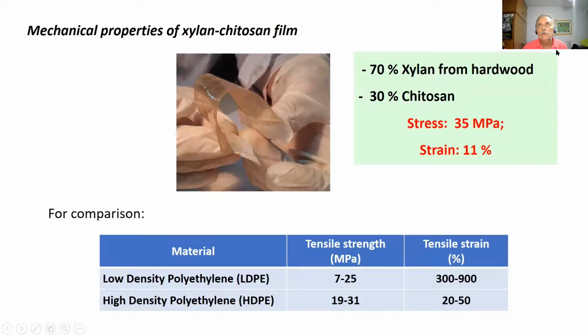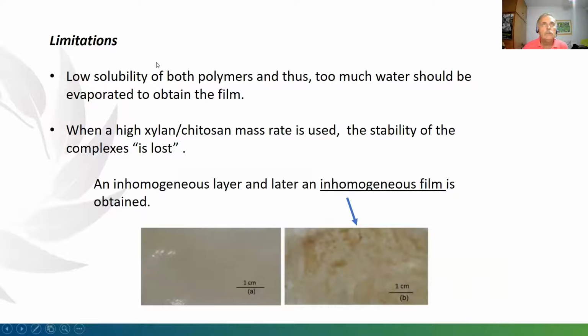And for instance, with 70% of xylan and 30% of chitosan, we have a stress of 35 megapascals and a deformation of 11%. This is not so far from commercial polymers, at least in strength and elongation, like high density polyethylene plastic. Which are the limitations of this xylan-chitosan system? First, low solubility of both polymers, and thus too much water should be evaporated to obtain the film. And when a high xylan-chitosan mass ratio is used, the stability of the complex is lost. So an inhomogeneous layer in a wet condition, and later an inhomogeneous film, is obtained.